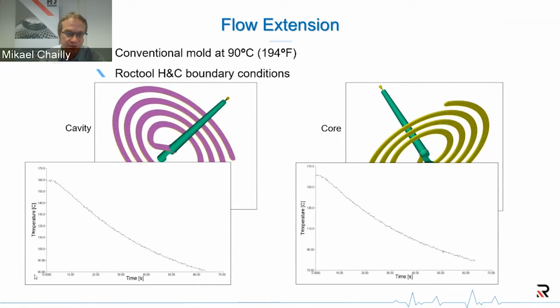So we have this conventional mold at 90 degrees, and we will compare it to what we have in the spiral flow mold, which is two-side heating with Roctool technology. What you see there is that we start with 160 degrees down to 80 degrees in this configuration. Typically the curves that you have are the ones directly obtained from thermocouples located within the mold from the trials.